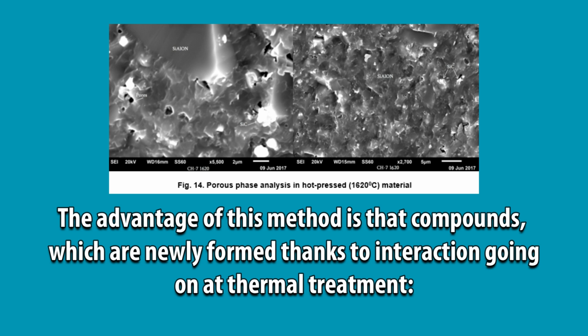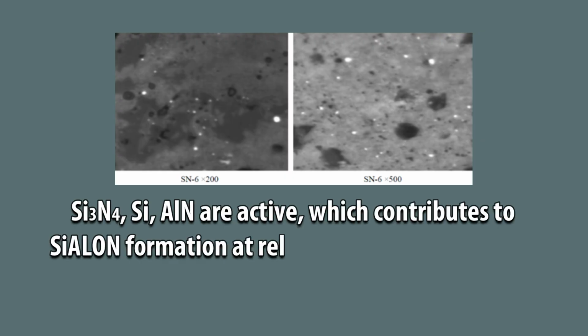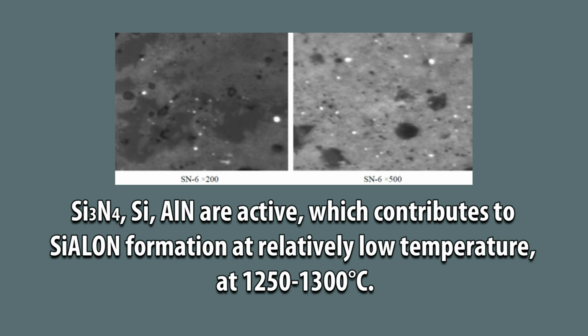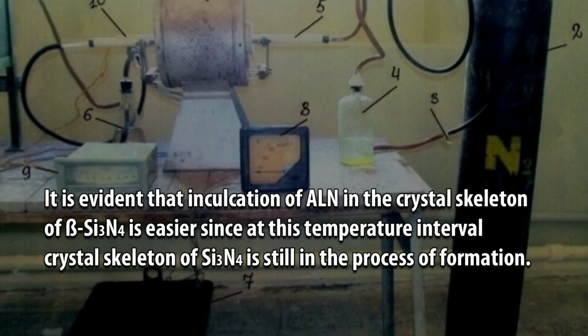The advantage of this method is that compounds, which are newly formed thanks to interaction going on at thermal treatment, silicon nitride, silicon, aluminum nitride, are active, which contributes to SiAlON formation at relatively low temperature, at 1250 to 1300 degrees Celsius. It is evident that incorporation of AlN in the crystal skeleton of beta silicon nitride is easier, since at this temperature interval crystal skeleton of silicon nitride is still in the process of formation.